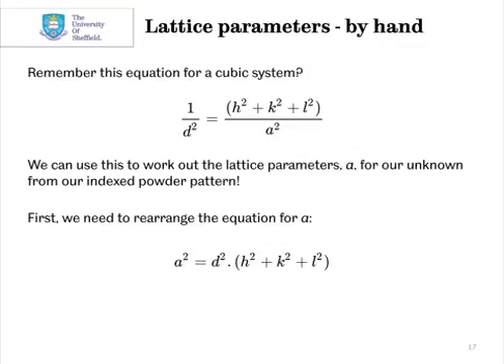So we've got now our peak positions, and we've got our Miller indices for this mysterious metal. We looked at this equation earlier on briefly: 1 over d squared equals h squared plus k squared plus l squared over a squared. We can use this equation to manually calculate the lattice parameter a for our unknown powder pattern. First of all, we need to rearrange the equation for a. So it becomes a squared equals d squared times h squared plus k squared plus l squared.